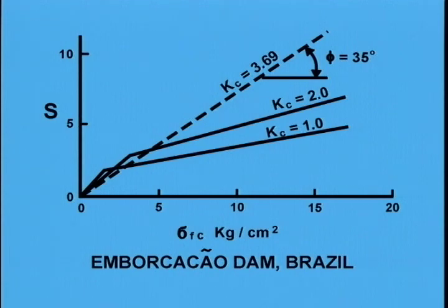Also shown are the S versus sigma fc lines for K sub C equal to 1. The steep initial lines represent the condition of no strength being attributed to tensile pore water pressure. The effective stress failure line is shown dashed, and for an effective friction angle phi prime of 35 degrees, its value is K sub C equals 3.69. K sub C values for actual cases generally fall in the range of 1.7 to 2.3. Strength values for K sub C values somewhat above and somewhat below K sub C equal to 2 can be determined by interpolation with the K sub C equal to 1 and the K sub C equal to 3.69 lines.